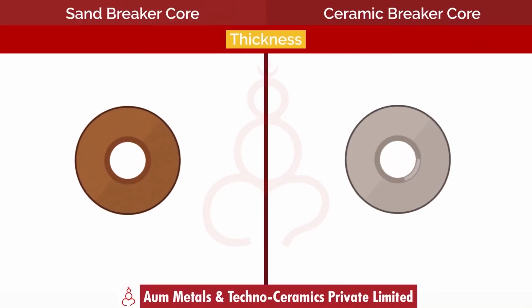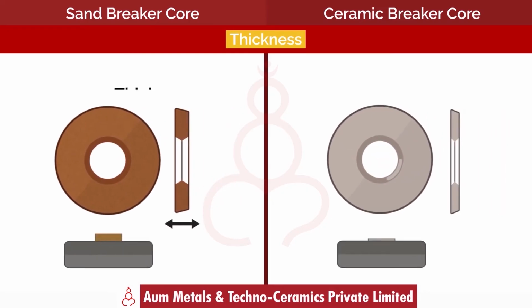These ceramic breaker cores are very thin, so they don't absorb much heat, and as a result, it doesn't reduce the efficiency of the riser. Not only does it not reduce it, it improves the efficiency of the riser.